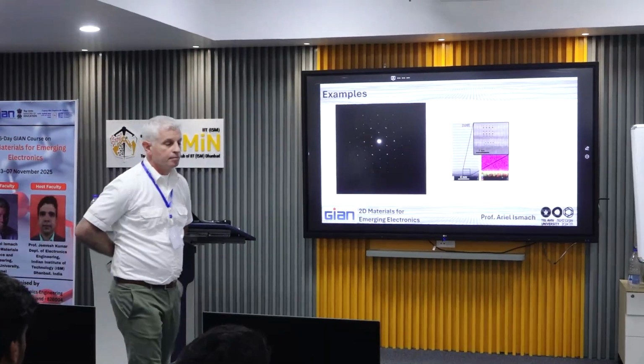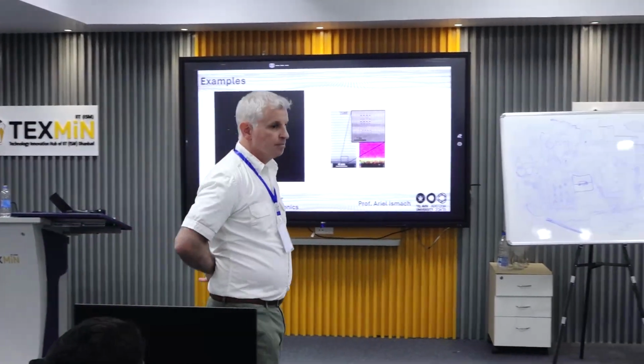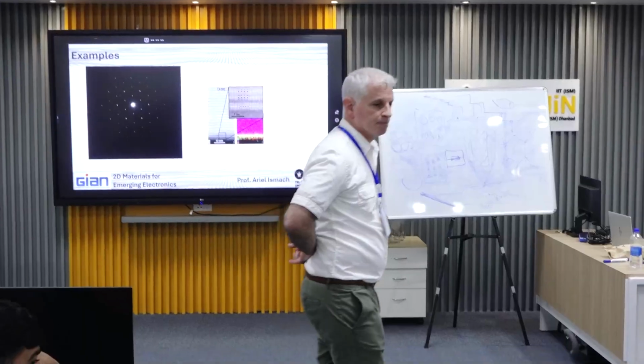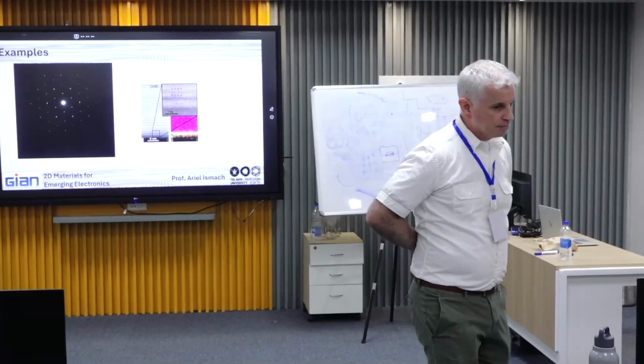You are talking about applying strain by stretching the substrate, for example. The force between the substrate and the sample is one issue. Well, you're right, so you need to be careful with that. But it's not stable. But if you have polymers, you might be able to catch it, at least at low strains. People have done it.